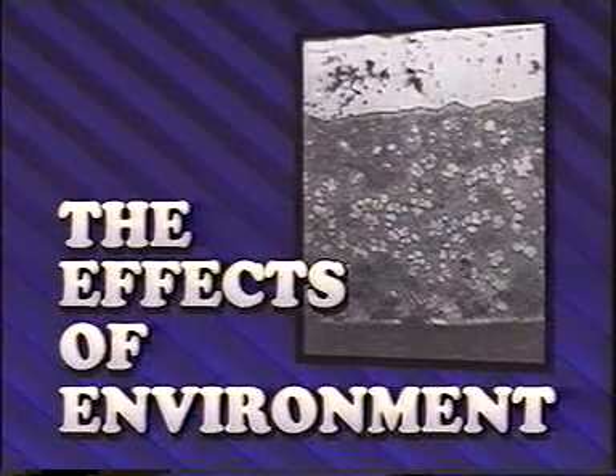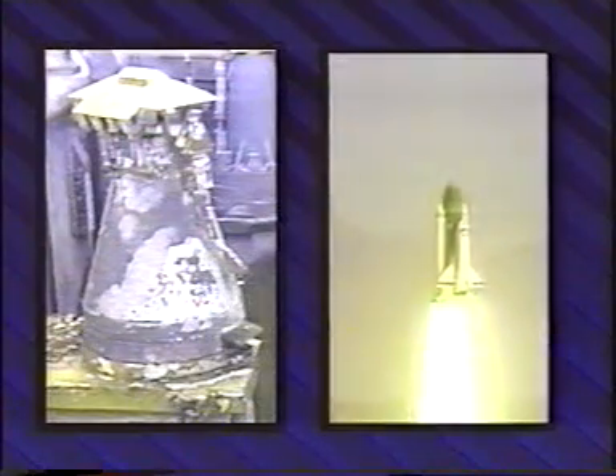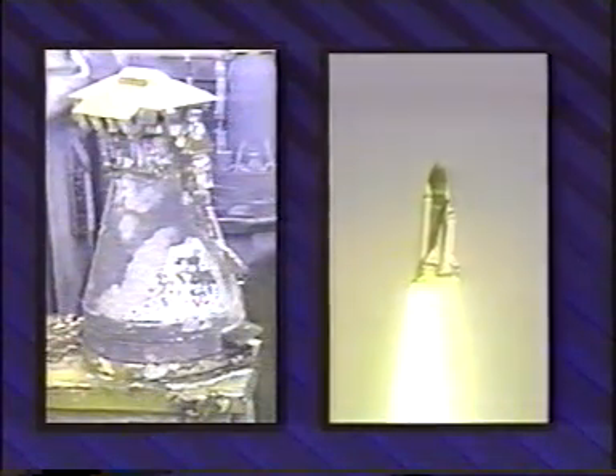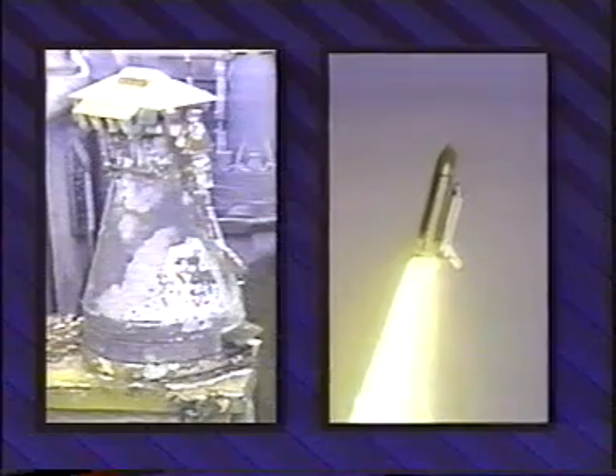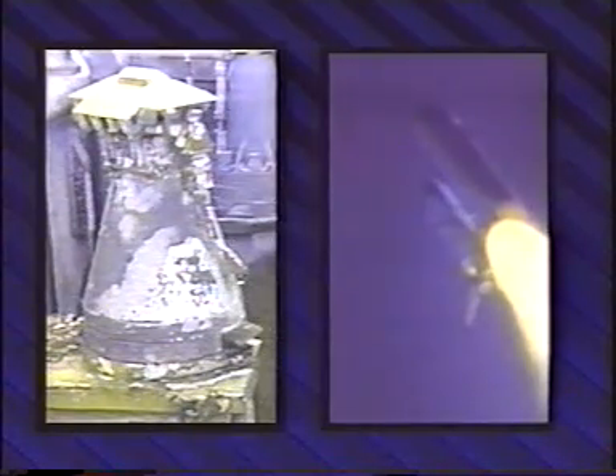The effects of environment. Environment and the interactions between surface and environment have a marked effect on the behavior of metals at elevated temperatures. In fact, the most common source of elevated temperature failure requiring premature replacement of a component is the environmental degradation of material. Environmental degradation of material causes far more elevated temperature failures than creep and stress rupture. In most elevated temperature applications, control of environment is essential, or the materials must be protected by coatings or self-protective